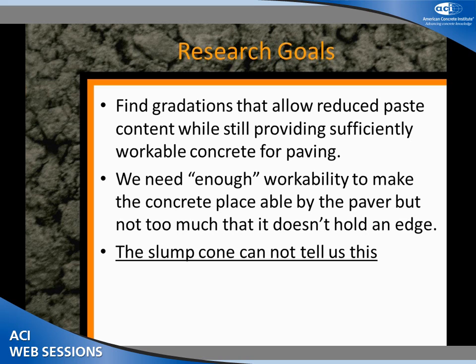So what are our goals? We want to find gradations that allow reduced paste contents for concrete pavements — it's all about concrete pavements. We need enough workability, but not too much. We want the concrete to be placeable and vibratable, but the concrete has to hold an edge. So we have a window of workability: it has to be workable enough to consolidate, but not so workable that as the paver passes you lose your edge and have to use side forms.